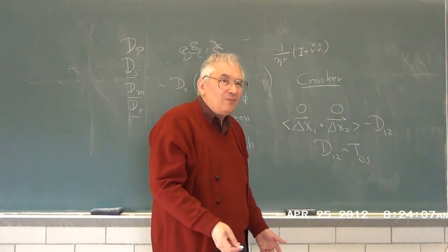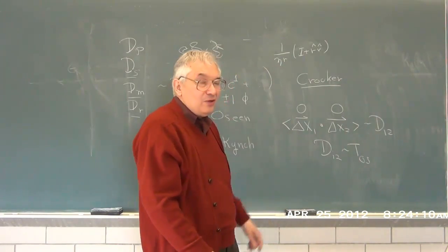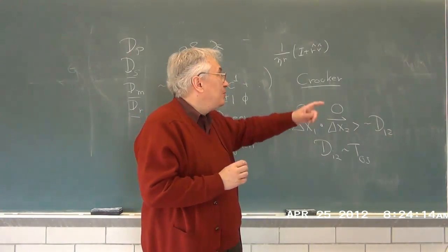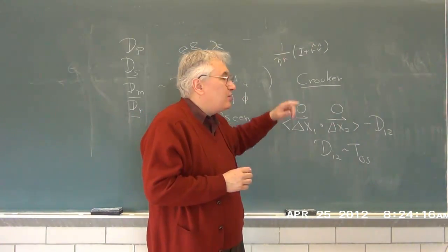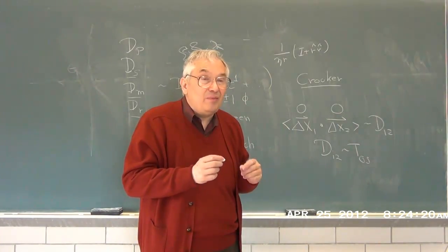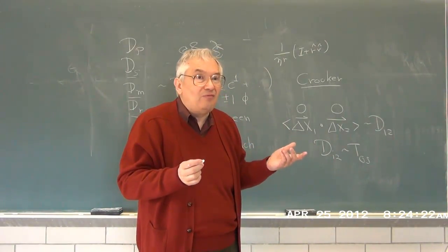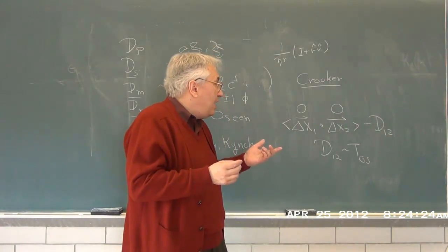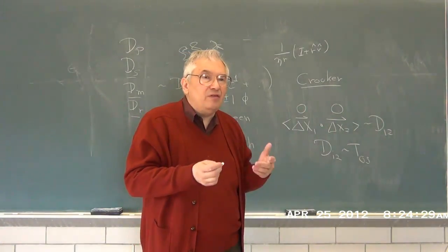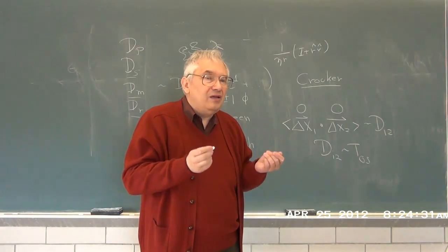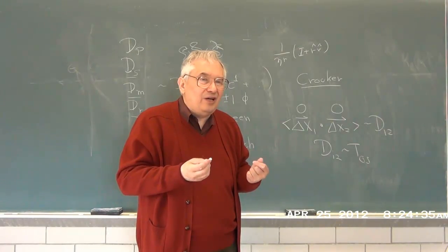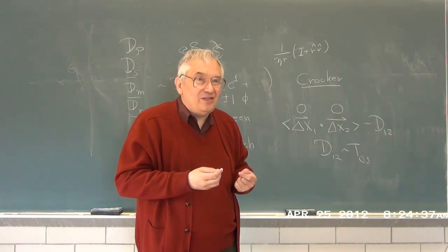Well, the experiment's been done. This form does seem to work, though the people who did the experiments were looking for eta, not asking if 1 over r was correct. At least they don't mention this in the paper. They may have known it was an issue and it was so obvious there was nothing to say. And what they find is a 1 over r dependence even for pairs of probes in concentrated polymer solutions. That is, people have looked directly for hydrodynamic screening and it is not at home.